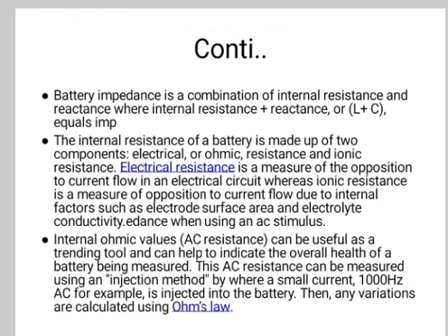Equivalent series resistance meters, essentially AC milliohm meters, are normally used to measure the ESR of a capacitor, that is, the equivalent series resistance of the capacitor. They can also be used to estimate battery internal resistance, particularly to check the state of charge of the battery rather than obtain an accurate DC value. Some chargers for rechargeable batteries indicate the ESR.